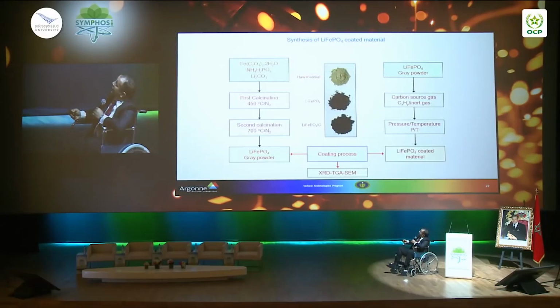Here is one example, just to show you the importance of nano and also carbon coating in improving the performance of iron phosphate. In this case, we use this type of precursor mixed with lithium carbonate. You calcine, and you do a second calcination, and then you do a carbon coating, obviously, and you end up going from a gray powder to a black powder.